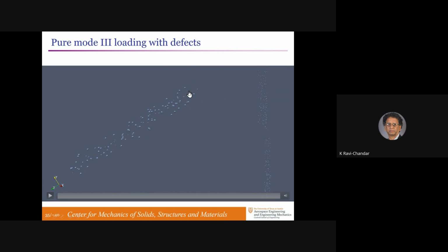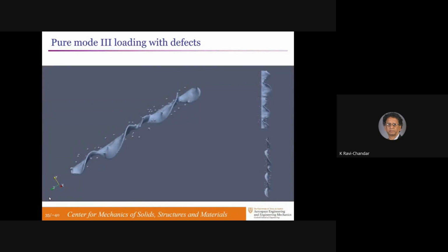Remember, if that defect system was not there, the crack would grow straight from the parent crack. Now, I don't show you the parent crack. It extends behind in that direction. This is the thickness direction of the specimen. And these defect elements are centered along the crack line. So, pure mode 3. And the cracks will become visible when new elements get damaged, not the old elements. So you could see the role of defects. They deflect the cracks from their original path along the line of symmetry.